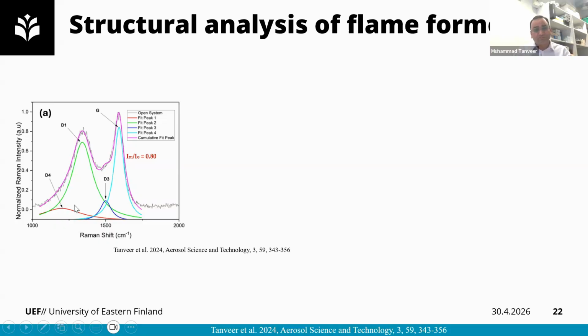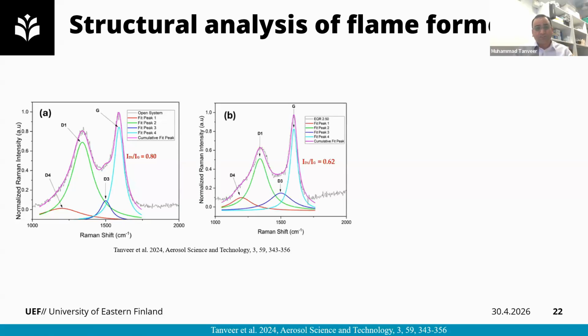into 4 peaks. This D4 peak is the extension of the D1 peak, and the D3 peak is basically the extension of the G peak. So this shows that this is part of G, as it shows the graphitic structure on the surface of PHs.